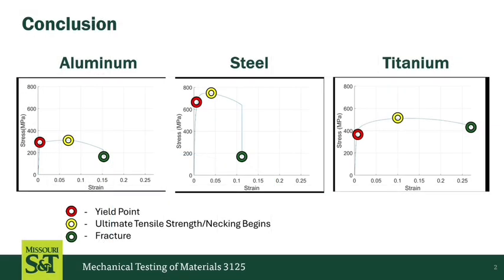As seen by these test results, steel was the strongest but most brittle, and titanium showed both high strength and good ductility. Aluminum had a lower strain than titanium, which suggests that it not only had lower strength than titanium, but also lower ductility. The ductility is still higher than the steel sample. The properties displayed by these tests are important because they show how a material responds to certain loads.